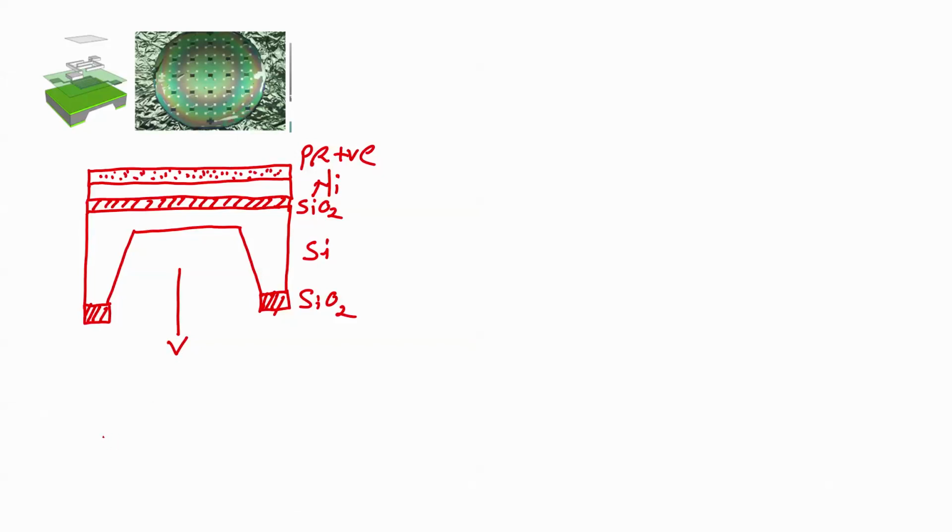Next step, we all know, I will just draw it on the same structure, right. After positive photoresist spin coating, soft bake 90 degree, 1 minute, hot plate, then we should have the heater, right, we should have the heater.